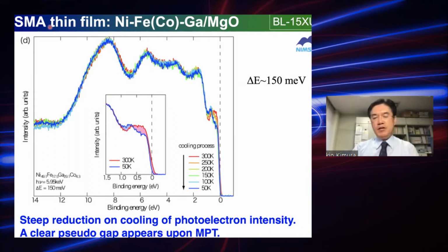So overall the density of states is identical for all the temperatures, but some changes are seen just near the Fermi energy. Here's a magnified picture of the density of states near the Fermi energy. You can see the steep reduction of photoelectron intensity on cooling, as you can see in the blue curve, and you even observe a pseudo gap upon the Martensitic phase transition. So this kind of experimental result suggests that the band Jahn-Teller effect may be responsible for the Martensitic phase transition.